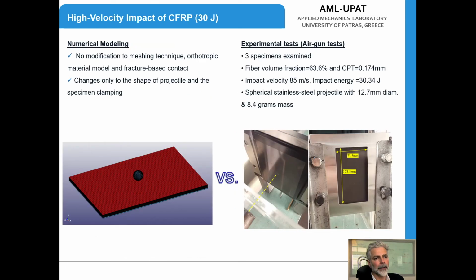What we saw earlier referred to low velocity impact. Here we try to simulate experiments of high velocity impact. Let's see the experimental data for the high velocity impact. We use an impact velocity of 85 meters per second. We have used a mass of 8.4 grams for the impactor, and this is a stainless steel impactor having a diameter of 12.7 millimeters.